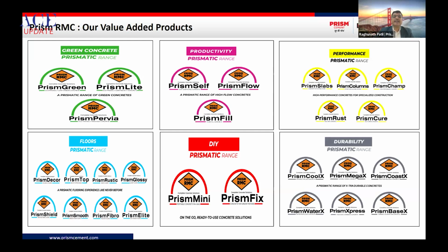This concrete can be de-shuttered early, because the strength we generally get is around 6 to 7 MPa after 12 to 15 hours. Generally, as per the IS code, de-shuttering is done after 16 to 24 hours. But here we have designed for long retention as well as early shuttering and early de-shuttering. That's why in 12 hours we get 6 MPa strength. Also, this column concrete is highly workable, so even with a little compaction, the concrete gets fully compacted. Like that, we have different products. I will discuss them in further slides.